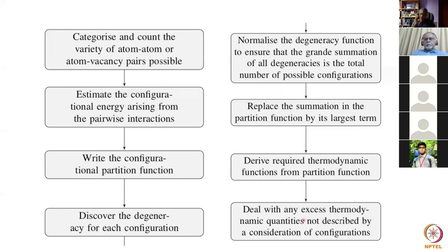And to be honest, all this talk about high entropy alloys, which I mentioned in my very first lecture, it's remarkable that they all assume the ideal entropy of mixing, whereas it is simply impossible in that sort of an alloy system to get an ideal entropy of mixing, okay? So someone needs to do proper work there to see whether these are really high entropy alloys or some wishy-washy low level of entropy because the atoms are not distributed at random.